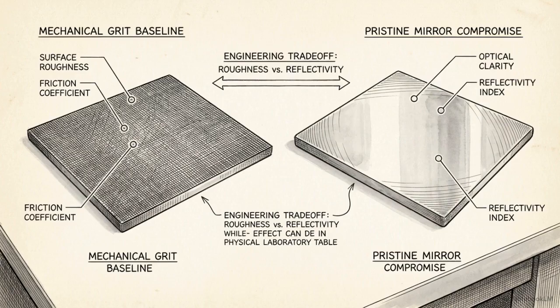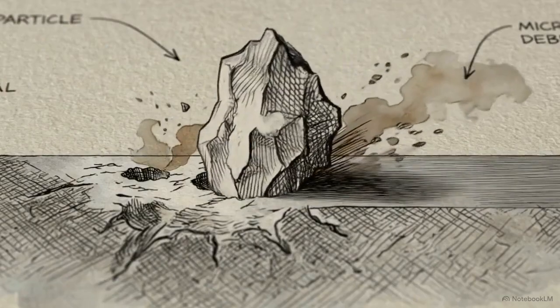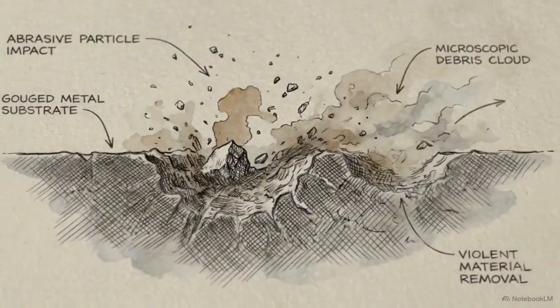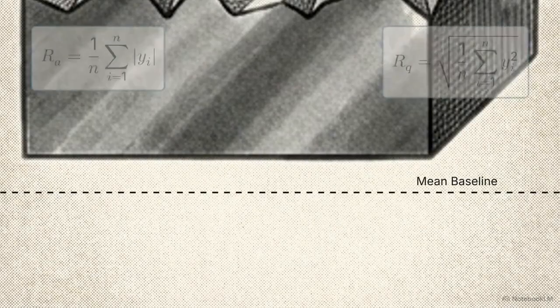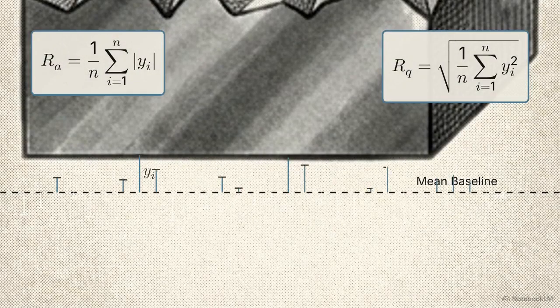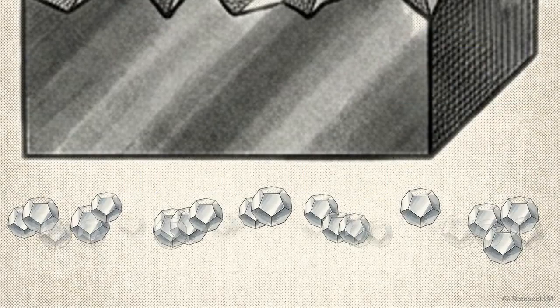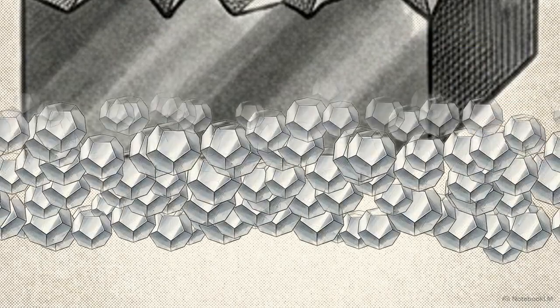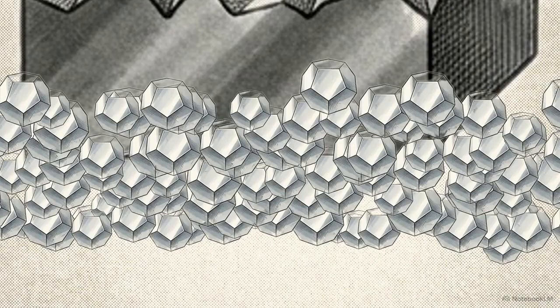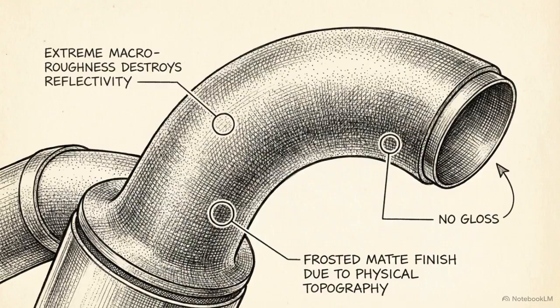We can see this compromise by looking at standard mechanical surface treatments. The first is sandblasting, a technique used to clear away passive oxide layers. Abrasive blasting violently and intentionally damages the bare metal substrate. This drastically increases the surface roughness parameters, measured as Ra and Rq values. Ra and Rq are metrics used to quantify the microscopic peaks and valleys on a material surface profile. This high roughness provides excellent nucleation sites, starting points for crystal growth, which creates high adhesion for hard, functional chromium coatings. But for decorative chrome, this macro roughness ruins the finish.